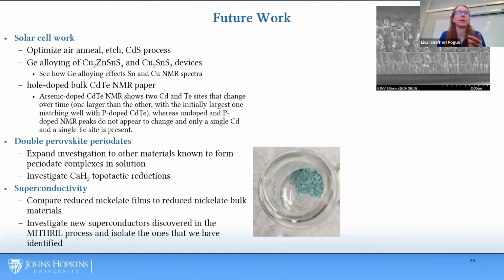Additionally, it would be interesting to see how this alloying might affect NMR spectra. Also, we've been looking at hole doped cadmium telluride. I had looked at various ways of hole doping cadmium telluride, because hole doping cadmium telluride is the major limit to cadmium telluride solar cell performance, because you can't get as large an open circuit voltage as you would like with these, because you can't get the Fermi level low enough. And if we could hole dope it better, we could get higher efficiencies.